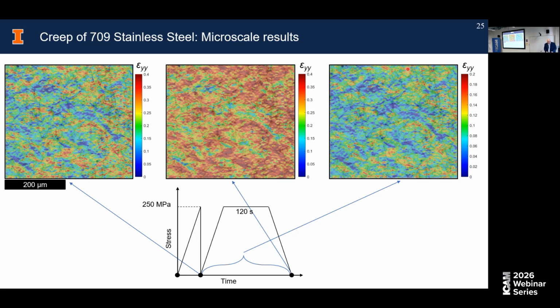And what we see here is the correlation between the strain fields. Again, this is all in tension, the dominant tensile direction. It's a correlation between the residual plastic strain field at this point, this image over here, with the plastic strain field at this point, which is this image over here, which is the combination of the plastic cycle and the creep cycle. If we look at the creep cycle only, that's correlating this point with this point. And if you look at the first and the third image, they're again very, very close. So really creep was essentially continued strain accumulation at the same point where plasticity had accumulated.